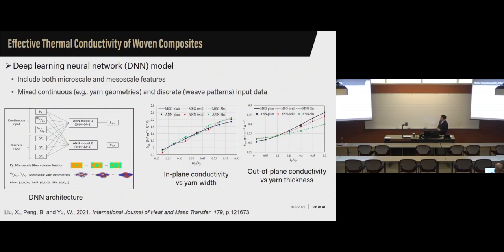The first example we did is to come up with an efficient surrogate model for thermal conductivity for woven composites, so that we link the micro scale effects like the fiber volume fraction, and also the woven pattern like plain weave and 5HS, and also the spacing of the yarns and the width and thickness of the yarns. So we build a model related not only to continuous variables, but also discrete variables of very different nature. And that's the power of machine learning. Traditional surrogate modeling techniques usually are not capable of that.